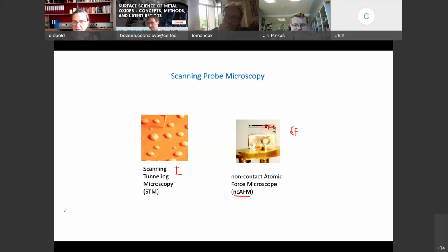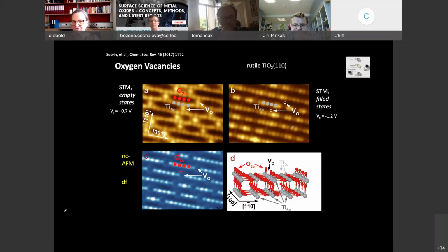Okay, now let's look at pictures of this TiO2(110) surface. This is the surface I showed you before, where I cut the metal to oxygen and oxygen to metal bond. Remember, we had titanium atoms that are 5-fold coordinated. We have oxygen atoms that stick out a little bit from the surface. They are 2-fold coordinated. They miss the titanium neighbor on top. And that's why people like to work with this material so much. The way we treat them in ultrahigh vacuum, we take out some oxygen, and they become a little bit blue, because we took out some oxygen from the sample. The oxygen we take out are all of the same type, these bridging oxygens, the 2-fold coordinated. We have made some oxygen vacancies.